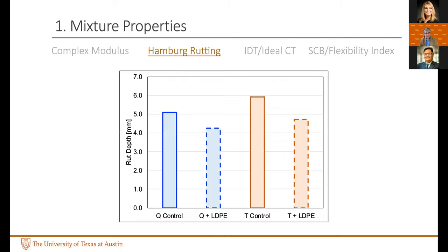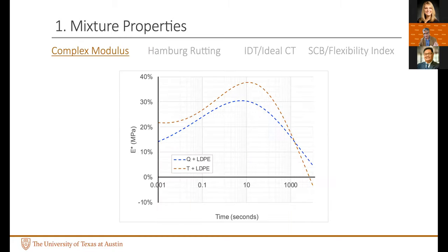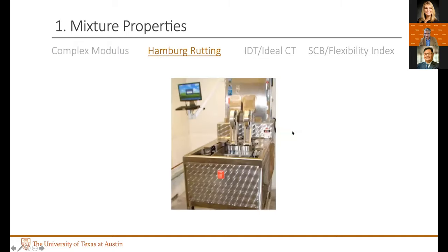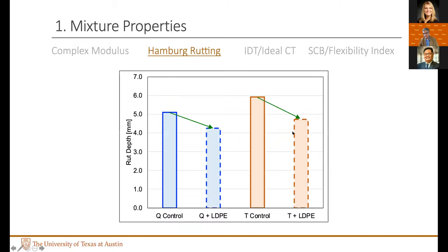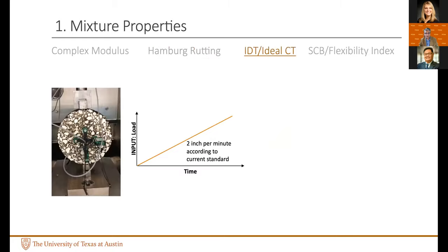Hamburg, you see the same thing, some improvement in rutting resistance. Keeping in mind that the Hamburg test is done at high temperatures, so if you're looking back at this curve, you're somewhere in this region where these effects are tapering off. But despite that, you see some improvement in the rutting resistance as you add these plastics. So that's a good thing. It's good for rutting, shows this effect on two different asphalt binder systems.